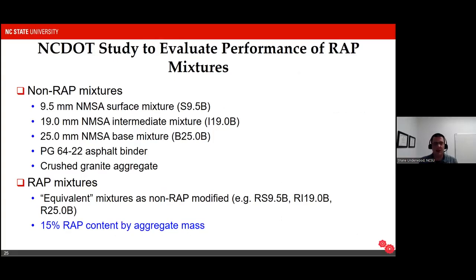Now, the RAP equivalent mixtures are produced using the same basic component materials, but using a mix design that incorporated RAP aggregates or RAP material into that mixture. Now, in our study, we used a fairly low RAP content, about 15%. Remember, this was done several years ago when that was a typical dosage rate in the state of North Carolina. That dosage rate has now increased to closer to, as you saw in the previous slide, about 24% on average. But we were looking at a fairly modest RAP dosage rate of 15%.